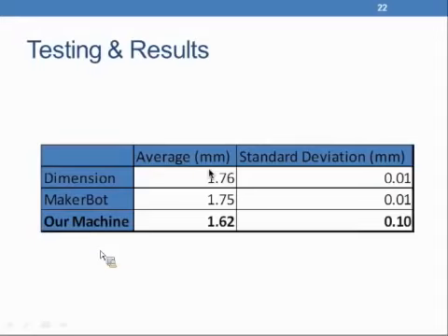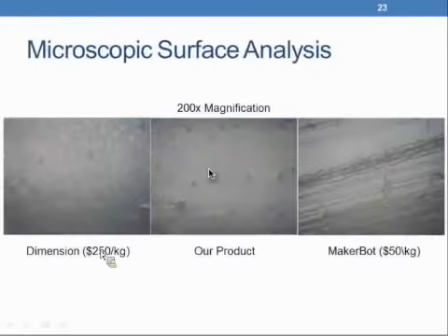Our variation is 0.1 millimeters plus or minus, and our average filament diameter on the sample that's being passed around is 1.62 millimeters. So as I previously discussed, we had those two effects, lengthening and necking. And because our die orifice was exactly 1.75 millimeters, you can see that the necking or gravitational lengthening effect dominated the production of our filament because our extruded filament nominal diameter is less than our target diameter. So our necking overcame the die swell.